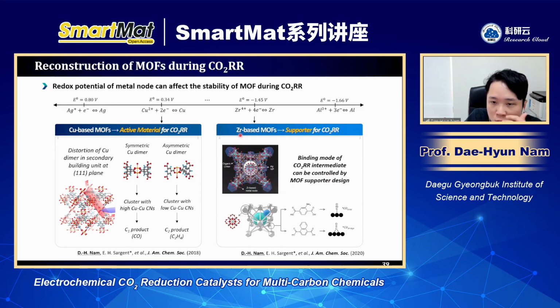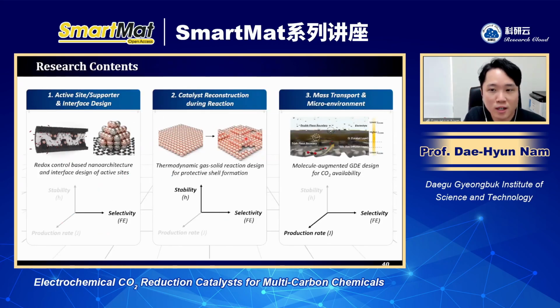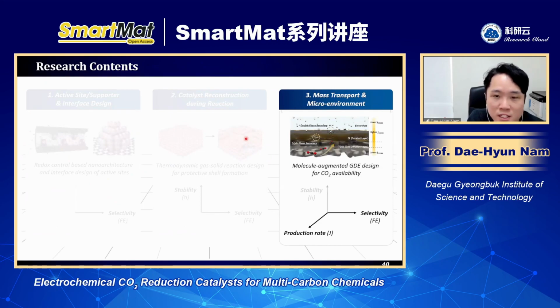And in this work, because zirconium is very stable during CO2R, we used it as a support for silver nanoparticles, and we found that according to the pore site design, we could control the CO2R activity of this silver. And this is how we can understand and manage the reconstruction of the material during CO2 reduction. So far, I presented the active site design and reconstruction issue. And sorry for the time, because it has already passed 57 now. So I'm going to present more briefly.